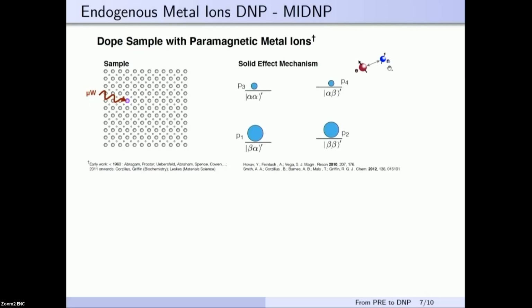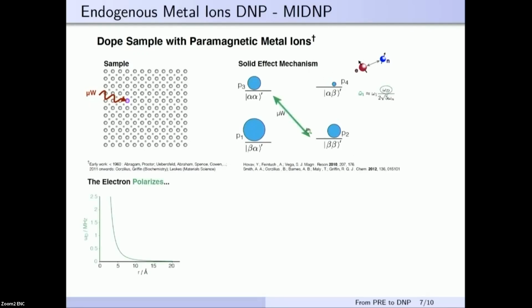And the idea in the DNP solid effect mechanism is to irradiate one of the formally forbidden transitions, either double quantum or zero quantum. If we are able to equalize the population of these two energy levels, we create a large population difference between the NMR transitions, which is what gives us the enhancement. Because this is a formally forbidden transition, the efficiency of this irradiation scales with the strength of the dipole coupling over the nuclear Larmor frequency, meaning that it will be less efficient for nuclei the farther away you get.